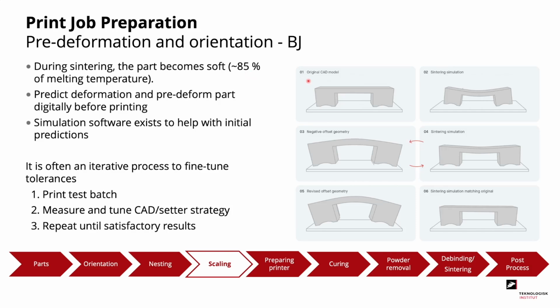So to the left you can see the original CAD model, and to the right of the figure you can see the sintering simulation where this part has bent down in the middle. To predict this deformation, you can pre-deform the part digitally before printing, and simulation software exists to help with these initial predictions. So in the middle of the figure you can see a negative offset geometry that results in a sintered geometry. This process of simulation typically takes several iterations.